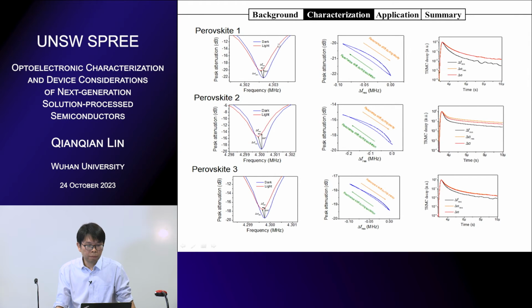And for the transients, we also analyze trap states. So for different perovskites, we measure the different spectra, and we get different decays from the phase and also the amplitude. So the phase is more sensitive to the traps, and the amplitude is more sensitive to the moving of carriers. So it's the mobility. So the decays could be different.